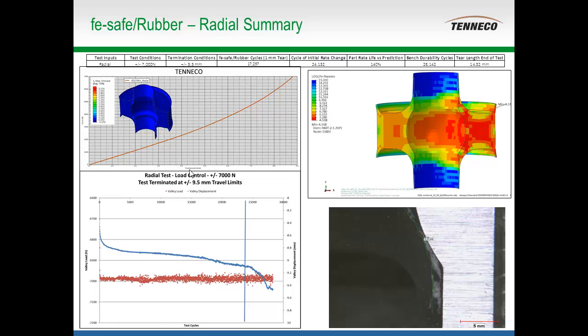Now, you can set the 1 millimeter crack length to higher values, but you have to keep in mind that there's no co-processing going on back with Abaqus to put the crack into your hyperelastic model to recalculate what your strain distributions will be around the crack. So once a small intrinsic flaw of 25 to 100 microns typically starts to grow into the macro crack region without remodeling it in Abaqus to input a crack and get how the strains are going to be affected, it starts to become inaccurate.